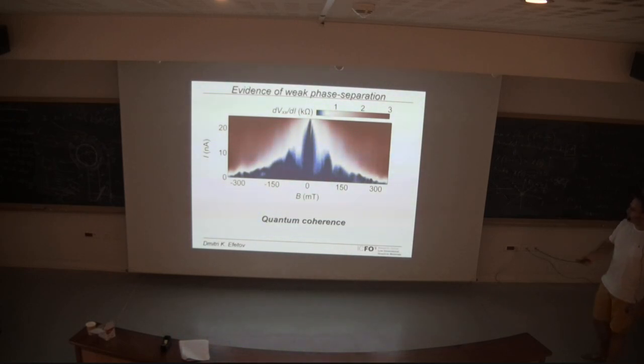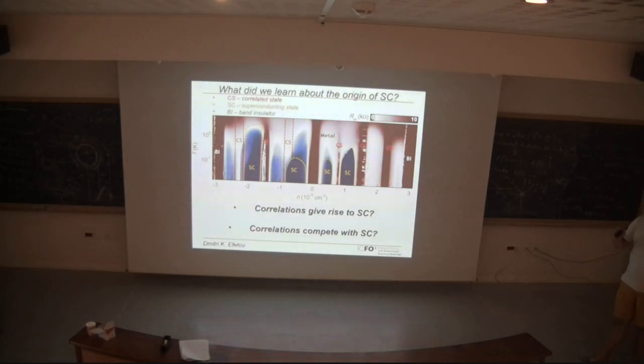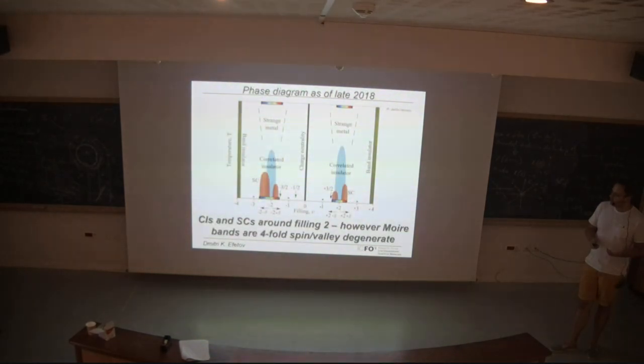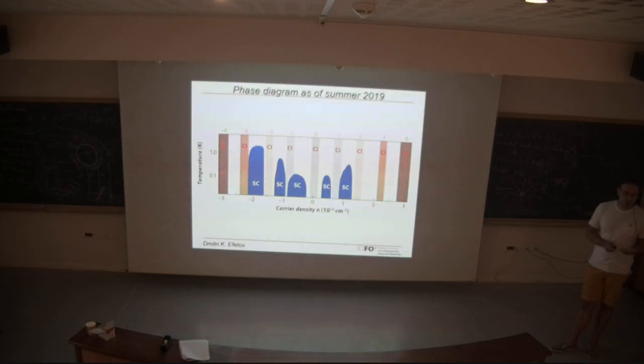Last but not least, our best evidence so far is this quantum coherence, this Fraunhofer pattern, which we can measure. It arises because we still have some very weak phase separation in the system, where the system basically breaks down into Josephson junctions in SNS regions. This is the phase diagram which we obtain, and of course the question arises whether this phase diagram has anything to do with that, or maybe it is slightly different and is more like that.